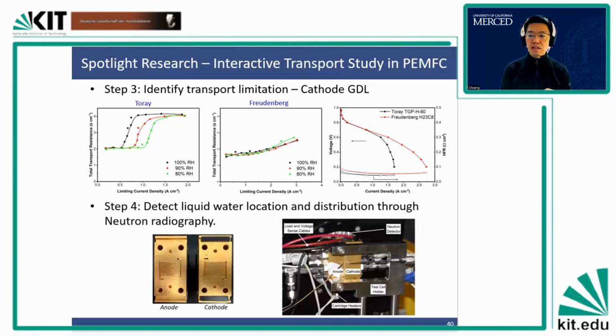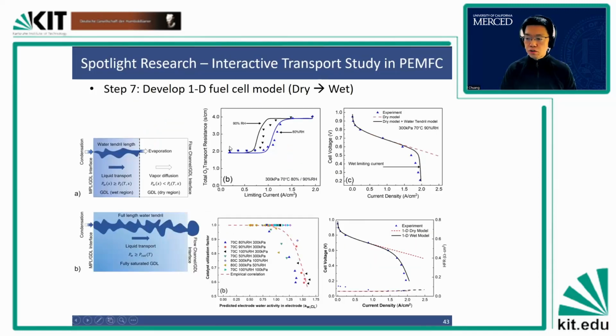Sorry, I didn't capture the name, but as the researcher from DSW was mentioning, hydrophobicity in this cell actually has a significant impact. One of our studies shows that if we have different levels of hydrophobicity, or even no hydrophobicity, these transport properties do not reach a plateau. I can show you this transition here. These are the materials. You can see that it goes from dry to wet and reaches a plateau. If you have a low level of hydrophobicity, or if you remove your micropores there, this transition will shoot up all the way rather than reaching a plateau. So yes, indeed, hydrophobicity is a critical factor in determining the liquid water condensation and the fuel cell performance in this case. Thank you so much, Professor.